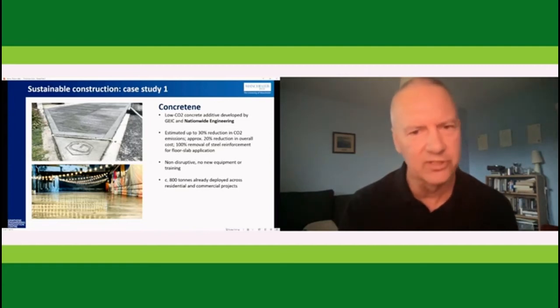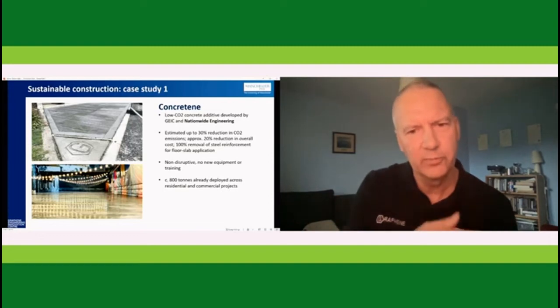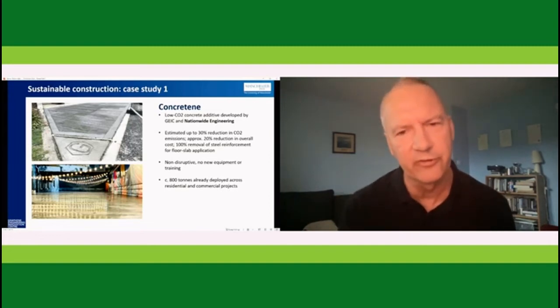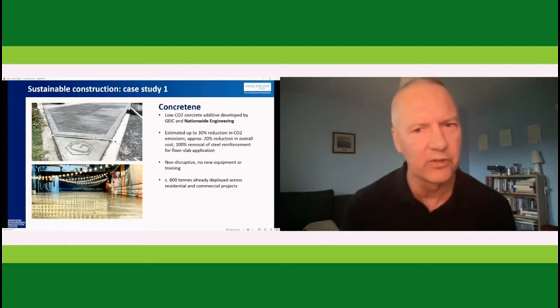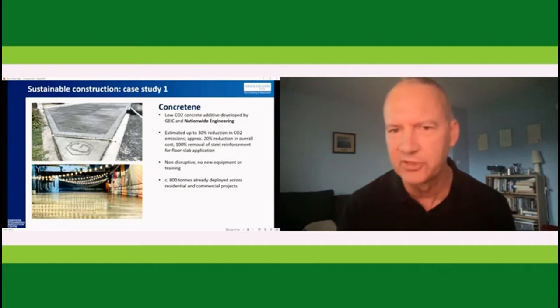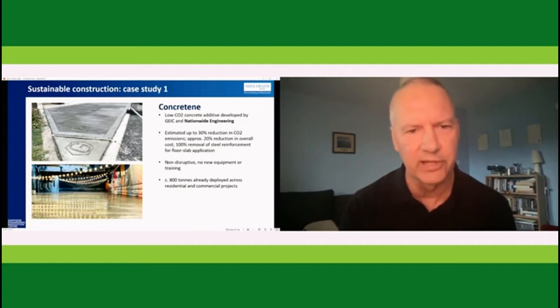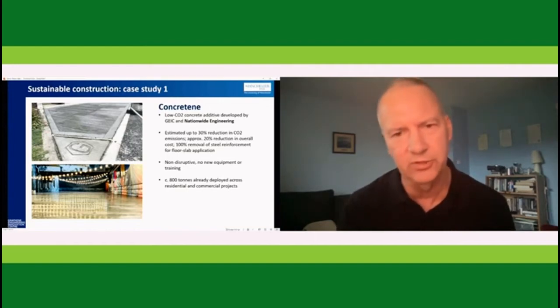And as an example, the slab of concrete on the bottom, when it started the pour at 10 AM in the morning, at 2 PM in the afternoon, they were doing the front end of the hall, and the polishing machines were actually on the back end of the slab on the afternoon of the actual pour taking place. So again, I believe that's quite unprecedented in terms of being able to do that in such a short period of time. And again, need to talk to the team, but they have a reduction in cracks, no expansion joints.